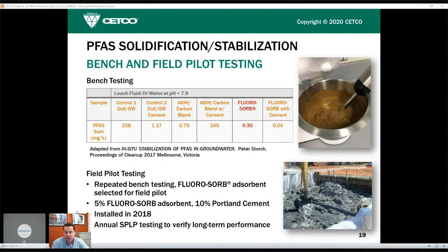So what you're seeing is some leaching data where Peter mixed the different medias in the soil. And in this particular study, he was looking at, for our media, 5 weight percent FLUORO-SORB and 10% Portland cement. And so what he found was that the soil by itself, if you try to do a leaching study, you saw 228 ppm in the leaching water. Very, very high concentrations of PFAS in the soil. And next, he looked at adding in cement, which reduced the leachability by a couple orders of magnitude. But still, you could see the concentration was somewhere around 1 ppm.